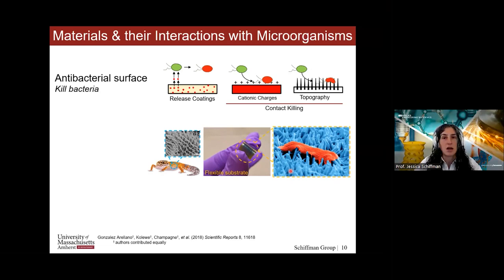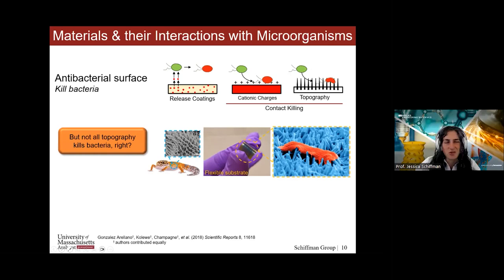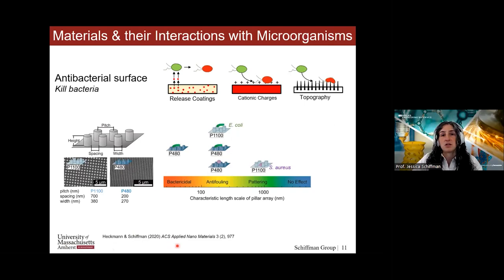So this leads me to a question: well, some topography can kill bacteria. Not all topography kills bacteria, right? So what happens if I change that topography? We looked into this in 2020 in this study where we used nanoimprint lithography to make these two different structures. Now, the structures are quite similar. We have these close packed pillar arrays. The material is made out of siloxane. It's PDMS. So PDMS, by itself, that chemistry doesn't kill.